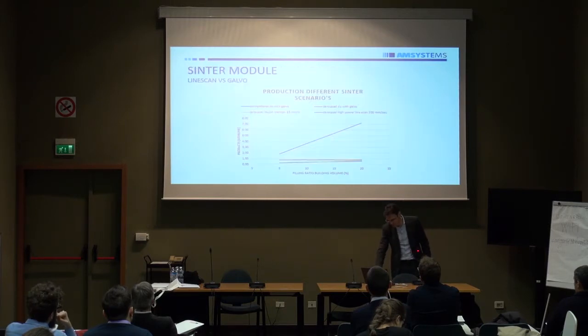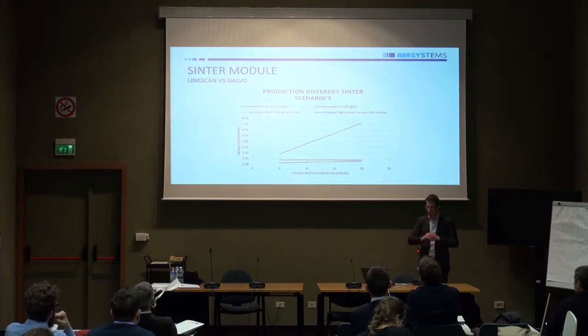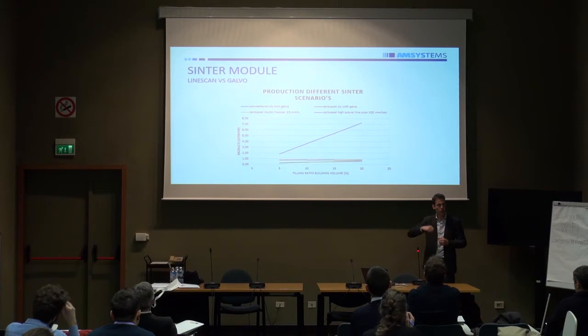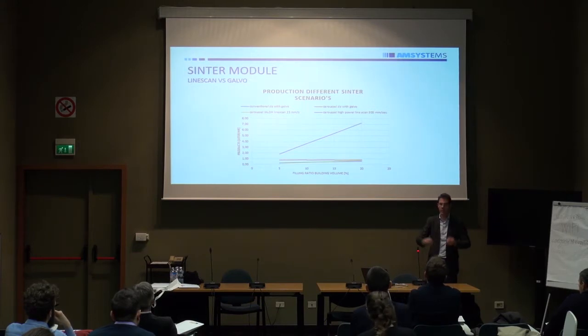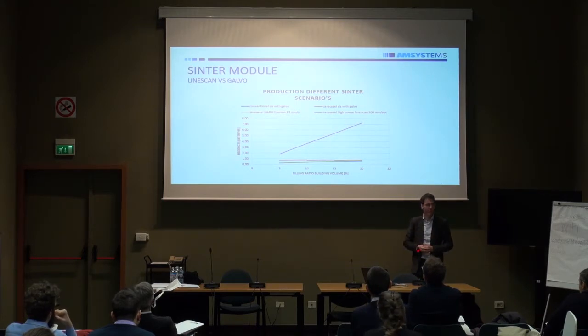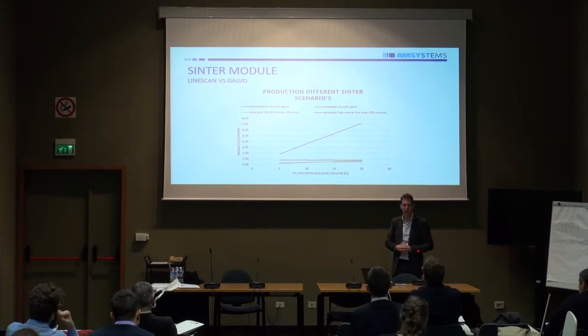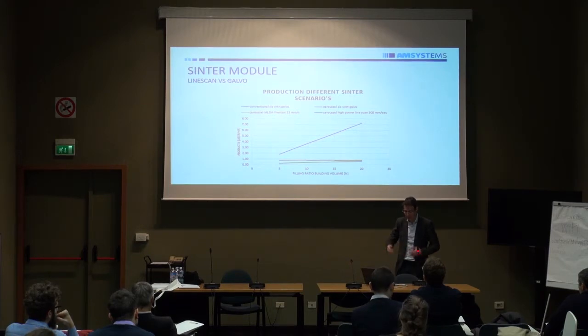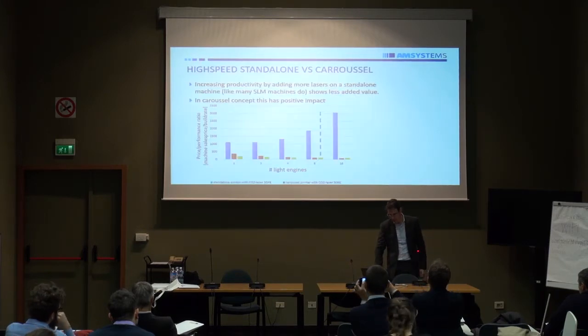I will show that with this graph. So for the CO2 laser, more fill ratio takes longer sinter times, but higher fill ratios with this line array doesn't matter. You can move it with the same speed, even when it is 100% filled. But we cannot make a job 100%. Then you make blocks. That's not the goal of AM. So you're stuck to this 5 to 10% for the moment, and you have to, with this as a given, compete with this CO2 approach.